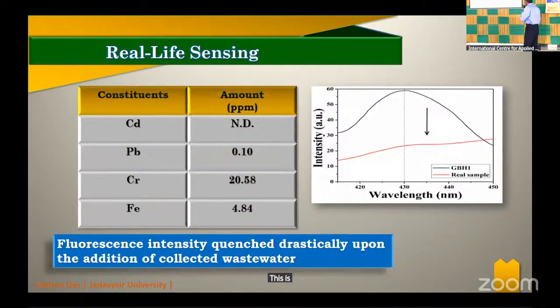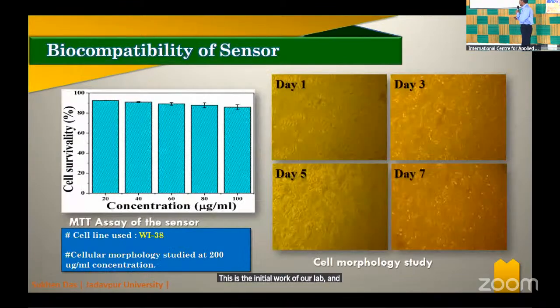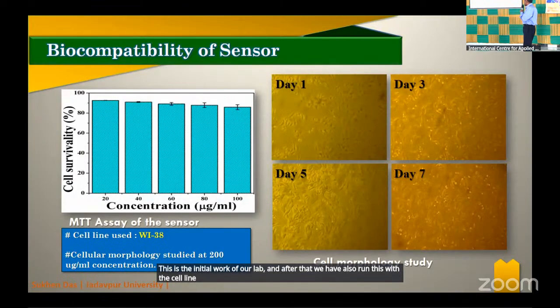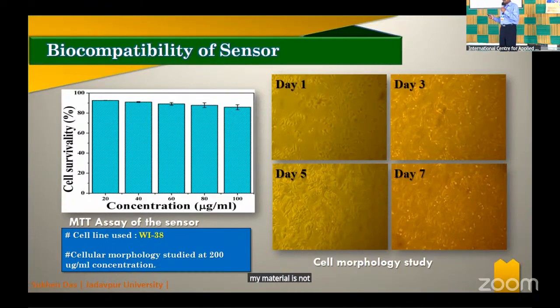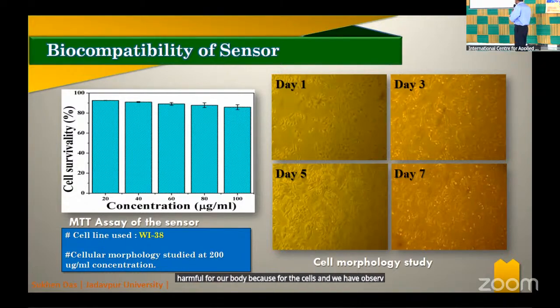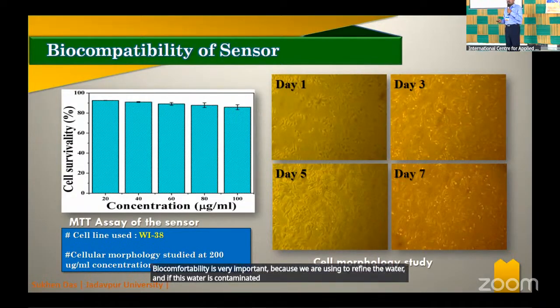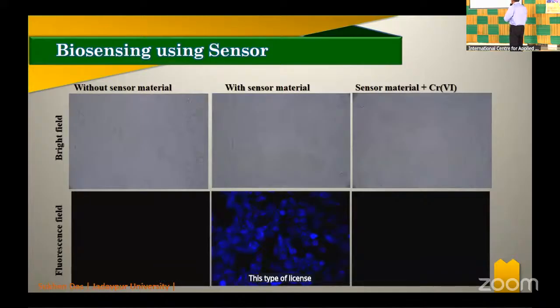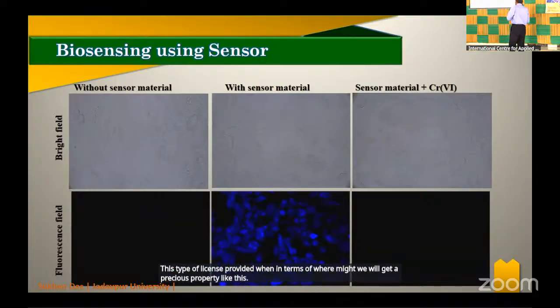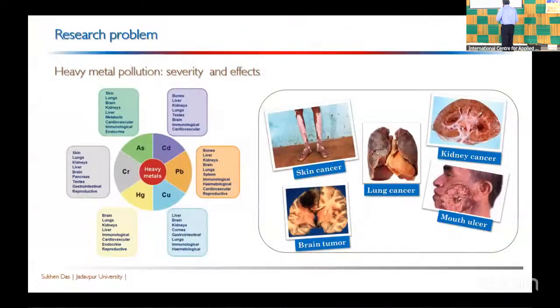This is the initial work of our lab, and after that we have also run this with the cell line WI-38, and from there we have seen that this boehmite material is not harmful for our body. The biocompatibility test is very important, because we are using it to refine the water, and if this water is contaminated again, then it will be difficult. That is why we tested with the cell line. This type of fluorescence property we find in presence of that boehmite, like this. So these are all the tests we have done.